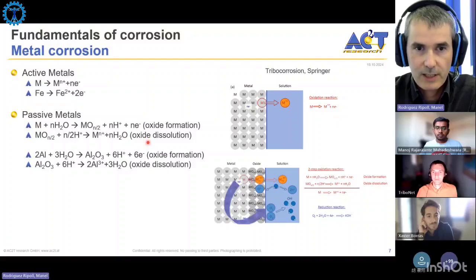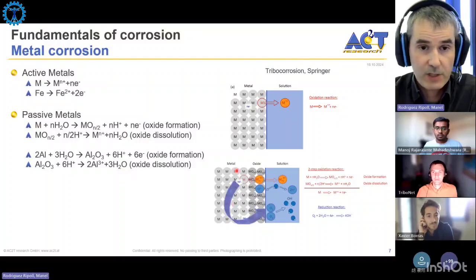This is, for example, the case of aluminum. That's the reason why aluminum components look shiny after the exposure to the environment. So aluminum reacts in aqueous solutions to form a spontaneous passive aluminum oxide layer. And of course, this oxide dissolution is a very, very slow process. So that's the reason why these metals do not really corrode.